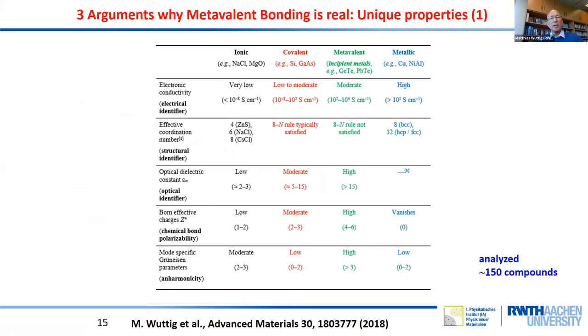And I think everybody agrees that a material with a very high conductivity is a metallic material, while if you have materials with very low conductivity, this very likely is an ionic material. And the current materials are somewhere in between. We can also use the effective coordination number, the optical dielectric constant, the Born effective charge, and the mode-specific Grüneisen parameter, as in total five different fingerprints for material properties.